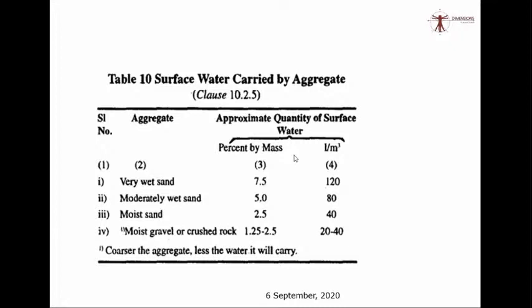My experience says for 2% of moisture, you have to be very careful. You should know whether the sand is very wet, moderately wet, or moist. Now, how to find this out? That is through experience. I will give you a simple trick to gain this experience. Go to your labs, take absolutely dry sand. You purposefully add 7.5% moisture to it, mix it, and try to have a feeler of how the sand will feel when you take a lump of sand in your hand. By doing this, you will have an experience of 7.5% moisture, which is very wet sand.